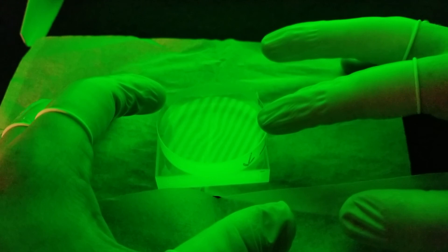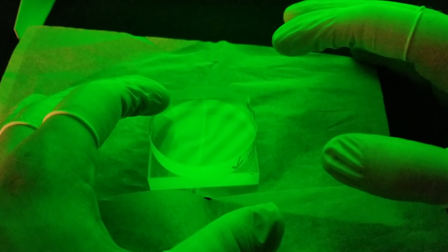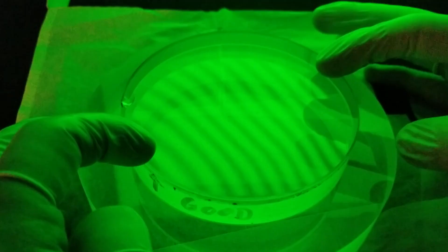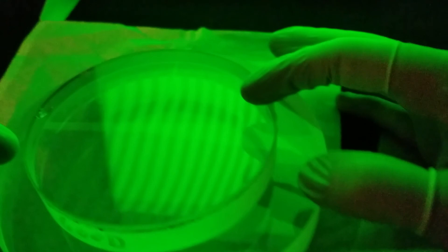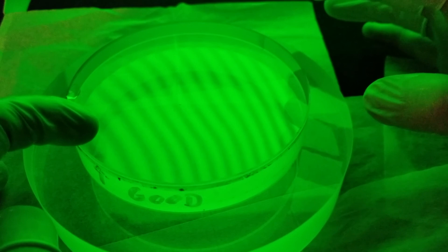There can be an open or closed side of the wedge. The side is closed if the pressure increases the number of fringes, and if the pressure decreases the number of fringes, it's on the open side. Depending on which side of the deviation of fringes the closed and open sides are, the defect can be identified as a bump or hole.